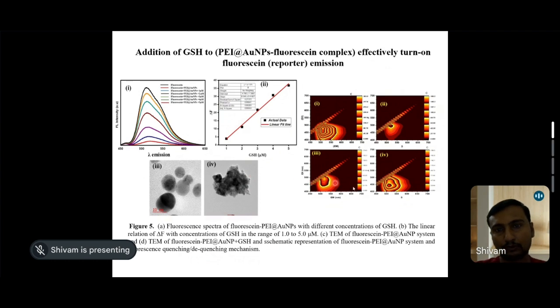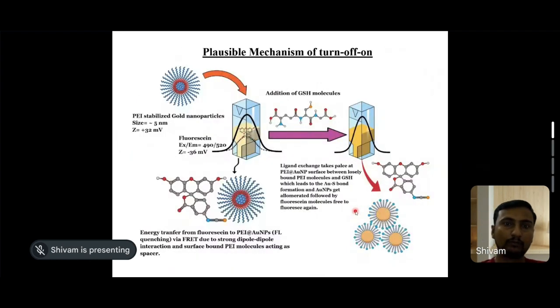You can also look at the 3D fluorescence spectroscopy. Here is the fluorescein emission after addition of PEI stabilized gold nanoparticles, and further addition of glutathione. It increases the quenched fluorescence intensity in a linear manner. Further, after adding another quantity of glutathione, the fluorescence of the system recovers. But what is the plausible mechanism behind it?